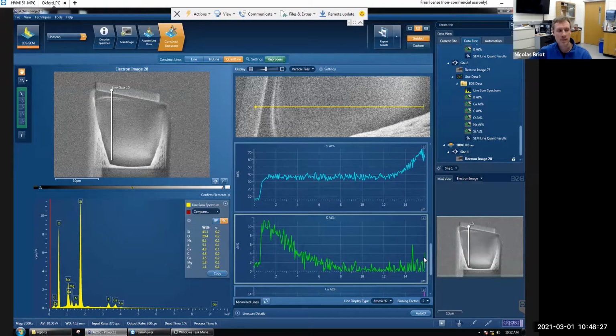What gives you the best result the fastest? The FIB is not super long, but it still took 40-45 minutes. And it was very possible that we could have seen that the potassium was actually much higher, and then we didn't see how deep it went, and then you'd have to make a much deeper cut, and it turns into a monster job, but it was good this time.